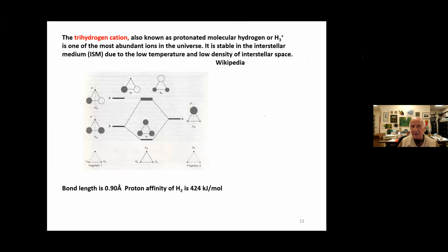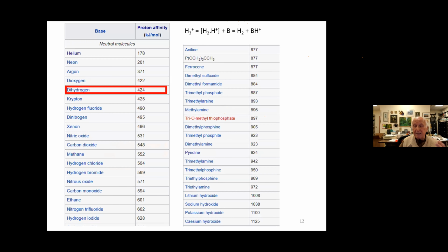Another example, just to finish the story of simple examples, is H3+. H plus adds to H2, giving off 424 kilojoules, 4 eV in a process. That's the heat of the reaction, H plus H2 to give H3+. The trihydrogen cation is probably the most abundant form of hydrogen in the universe, rather than H or H2. It's a very stable molecule, but you have not only not seen any bottles of H3+, but also there are no molecules that are stable, that are complexes that bind H3+ in any way. The reason is, it's easy to see what's happening. The H3+ is very exposed and very stable, but very reactive.